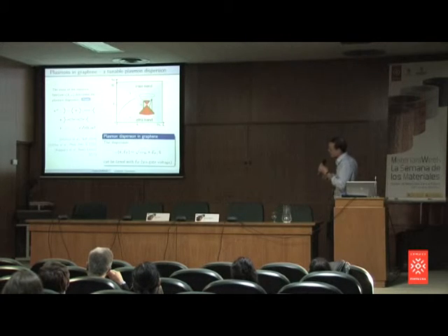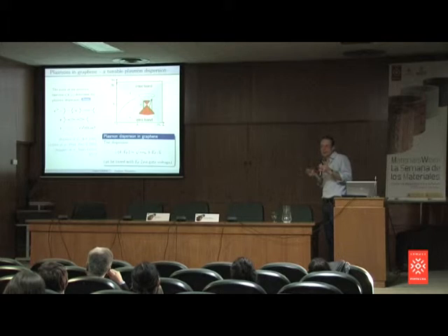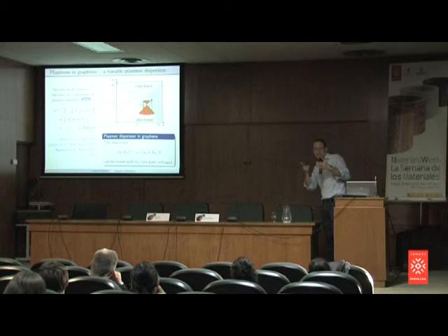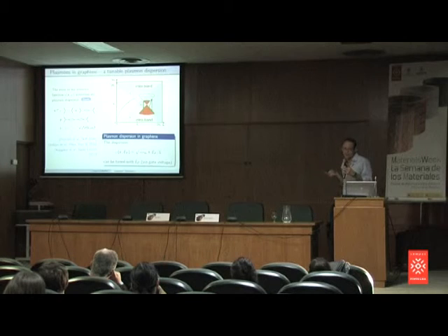Well, okay. To calculate how the plasmon really looks like, we have to think about how two electrons in graphene interact with each other. And this happens as in any conductor. There are lots of electrons, and if one electron is here and the other one is here, then their interaction is screened by all the other ones in between. And the details of how this happens is usually described by some dielectric function.